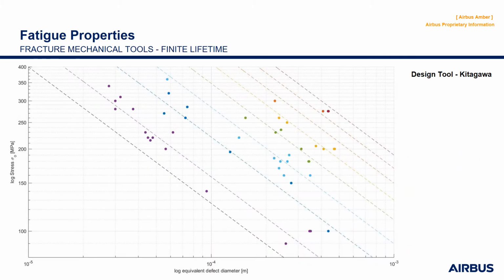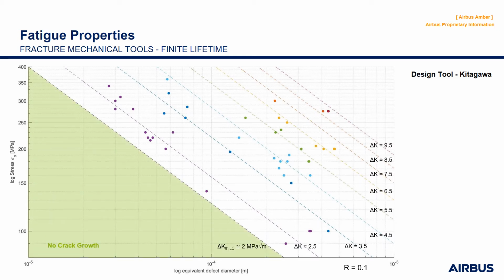We elaborated the Kitagawa diagram for our additively manufactured Scalmalloy. Originating from the various crack initiation sizes, mostly lack of fusions, and the long crack threshold value, which is approximately 2 megapascal square root meter for an R value of 0.1, we can identify three different areas in this diagram. Firstly, the load where no long crack growth will occur as a function of the defect size.